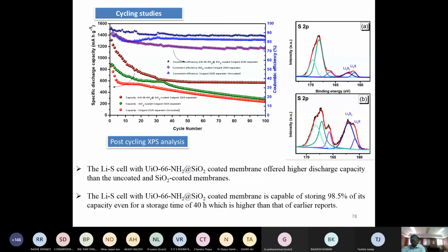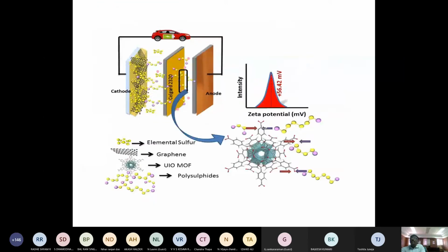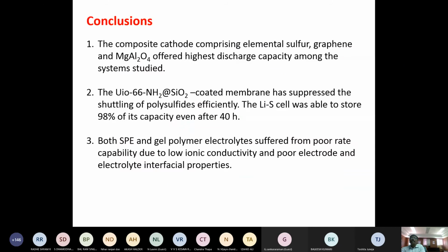And this is the charge discharge of the UiO, and we have finally made the XPS analysis to see whether the polysulfides are captured. Yes, of course, sorry, the B shows it, because when we made the XPS studies on the membrane, we found traces of lithium polysulfides in our XPS data. So this is the schematic diagram of how the polysulfides are attracted by the coated MOF, metal organic framework. So now I would like to conclude the second part.